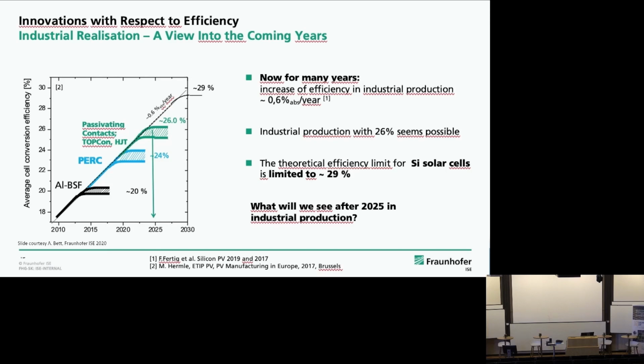Simply go away from these contact points by making the passivating layer so thin that carrier tunneling can make the contacting. So preparing the whole backside of the wafer as a tunnel oxide contact, and then of course you can get rid of the laser produced metal points, and therefore TOPCon technology allows to go up to about 26%. The alternative is heterojunction.